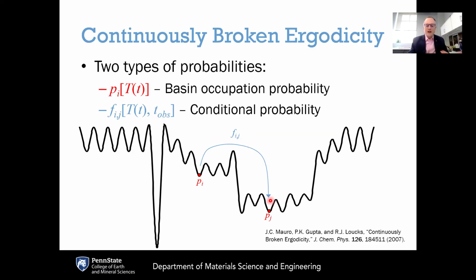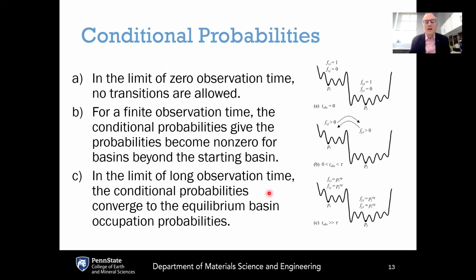And this is a valid framework regardless of the topography of the landscape, regardless of the Deborah number or the time scale in the system. If you have a system that is ergodic, this would recover that ergodicity. If you have a system that is fully non-ergodic, it would account for that as well. And then everything in between. So, for example, if you have the limit of zero observation time, if you allow the system zero time to evolve, that means that whatever basin you start in, that's where you end up in, right? Because zero time has elapsed, and that means the conditional probabilities, F_ii, would be equal to 1, because if you start off in i, then you end up in i because zero time has elapsed.